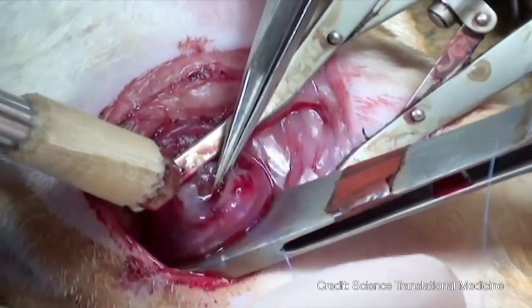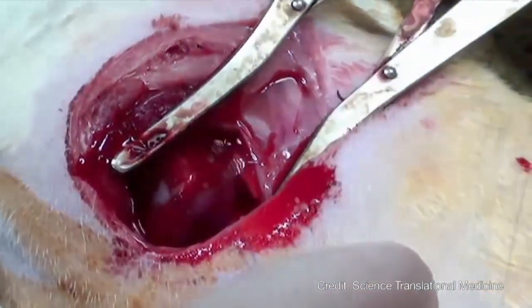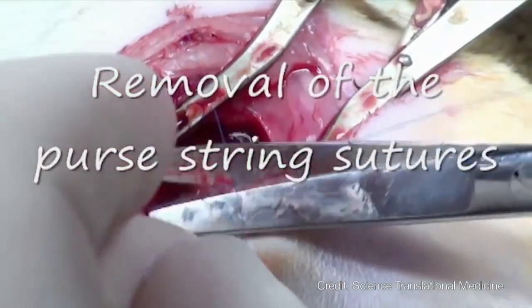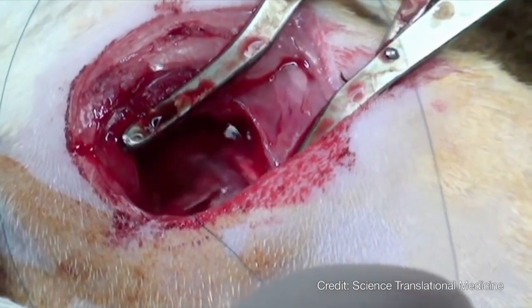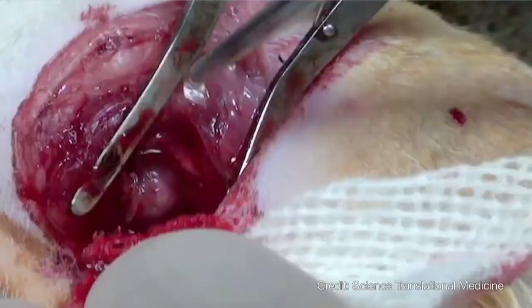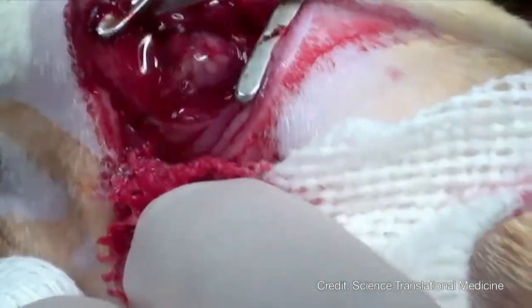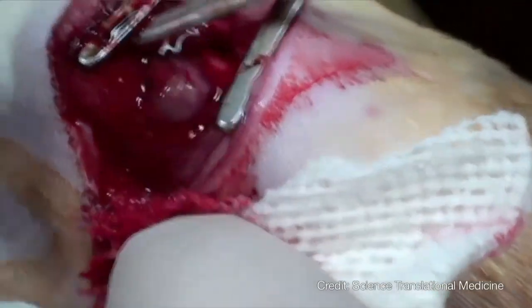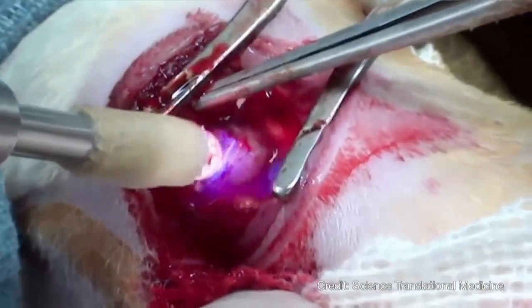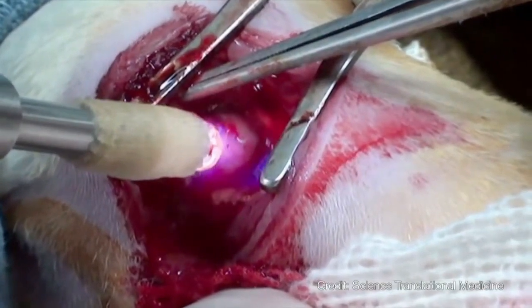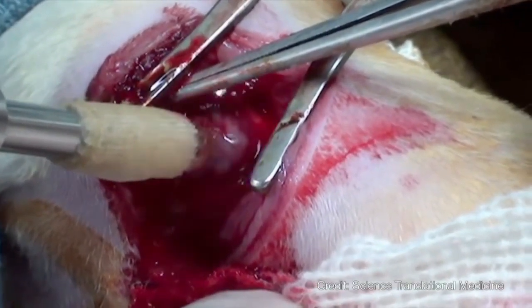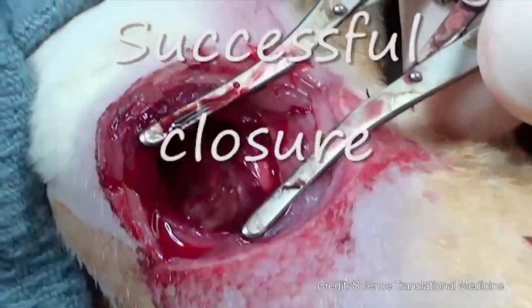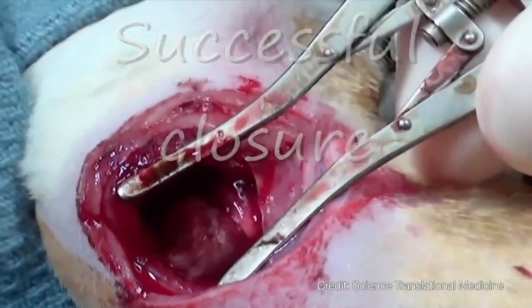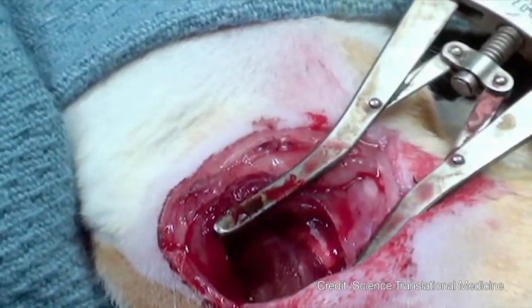We didn't know what to do. We had to act fast. So we removed the suture, and we scrounged up as much glue as we could find. We put it onto a spatula, and then we applied it to the leak. And it did exactly what it was supposed to. It repelled the blood because it was hydrophobic. It remained in place because it's viscous. Enough time for us to shine the light. Following another 5 seconds, we end up with a perfect seal. We took these animals out 6 months, and they did fine.